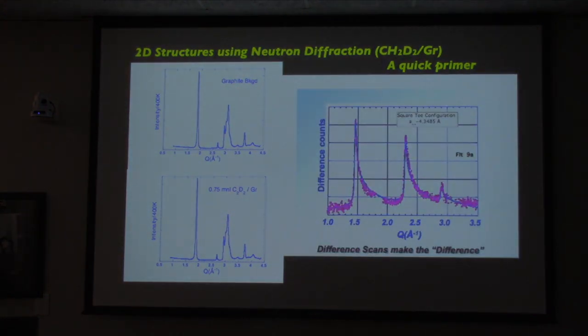So there are two things that you should see there. One of them is that you notice that there is a difference. The other one is that the shape of this particular diffraction pattern is not symmetric. And that's because this is only a single layer of atoms, and in fact, you only have two Bragg conditions that you have to satisfy. So only the projection of your rod in reciprocal space, because there's a bunch of rods, only the projection on the scattering plane has to satisfy what's called Bragg's law. Now I know that's a lot of words and that's tough, but you should notice that it looks like sawtooth curves. And that calculation is one that we've done years ago.